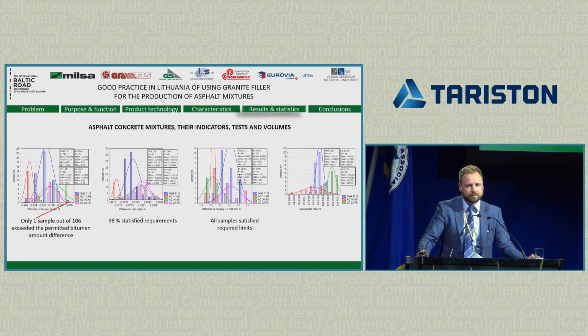So the main thing that shows the quality of asphalt as a product is the compaction ratio. So from all 4 mixes, and I want to say those are top layer mix, inner layer mix, SMA mix, and base mix, only 3 samples did not satisfy the requirements. And it might be for several reasons, maybe some weather condition or some technology.